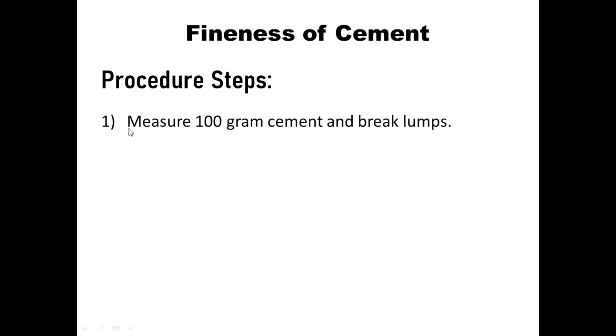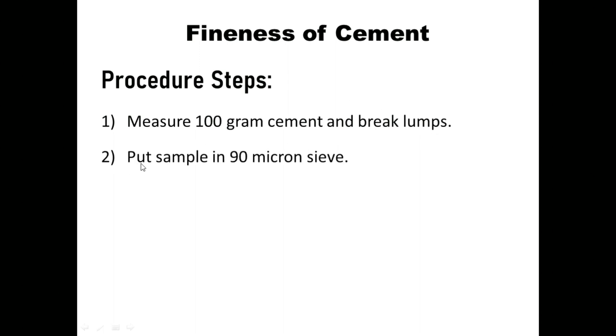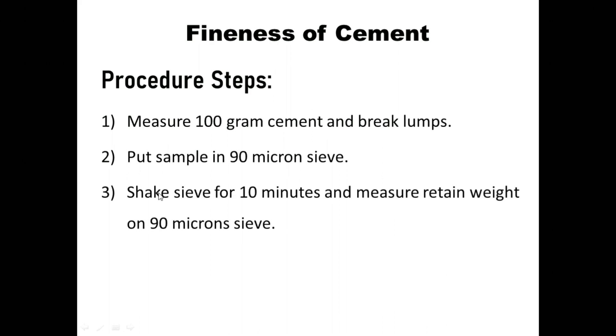For the procedure of this test, first we need to measure 100 grams of cement and break any lumps if present. Then put the sample in the 90-micron sieve and shake the sieve for 10 minutes.